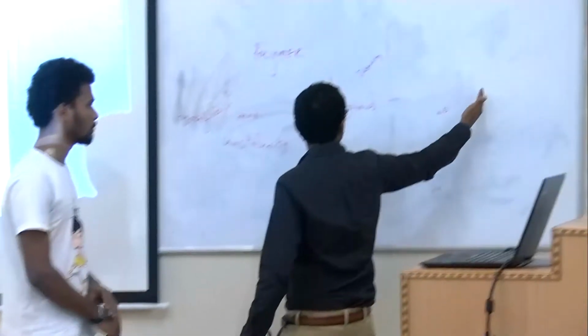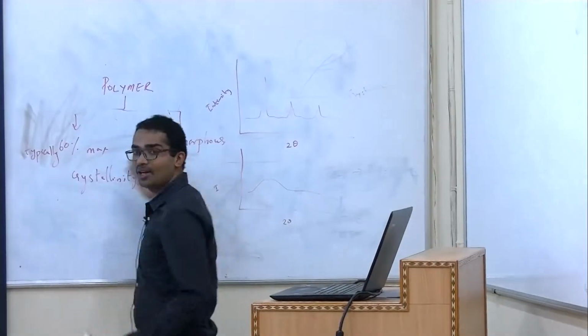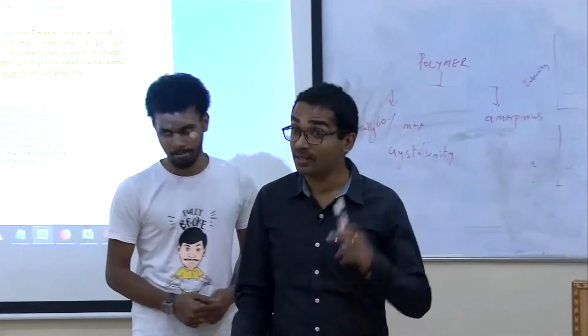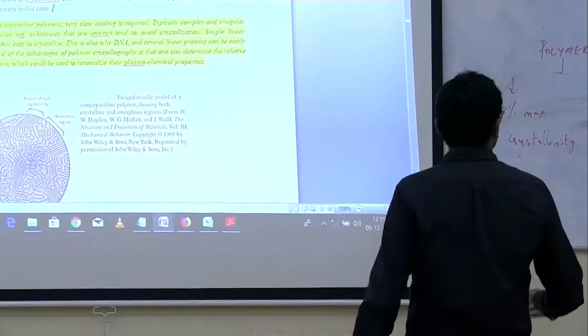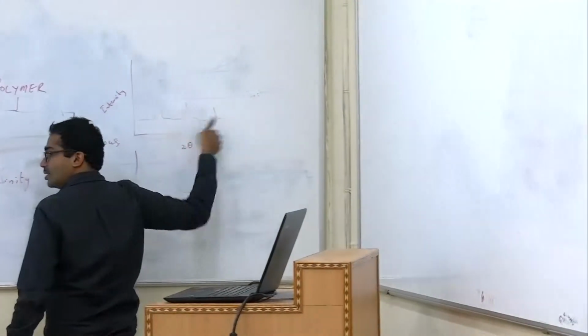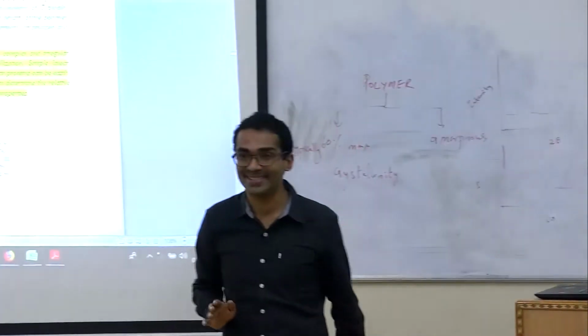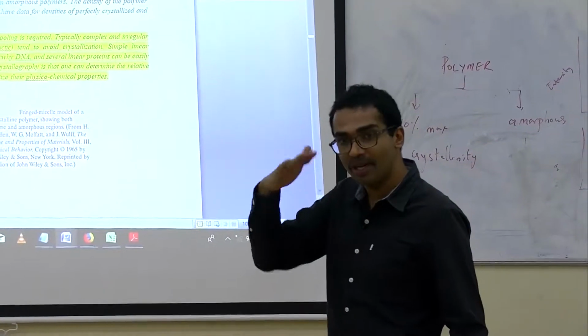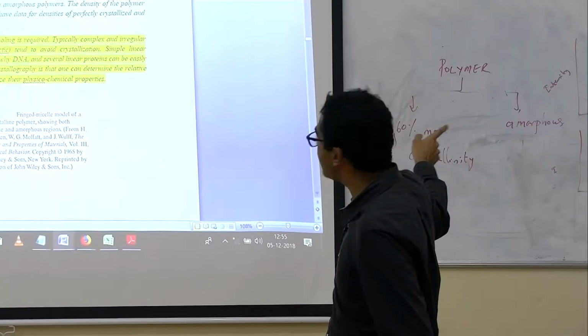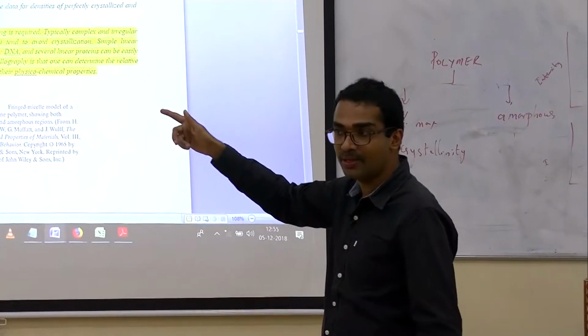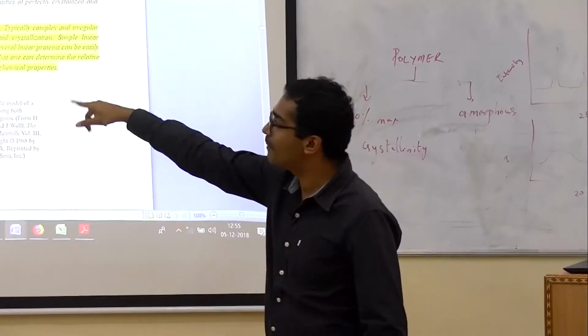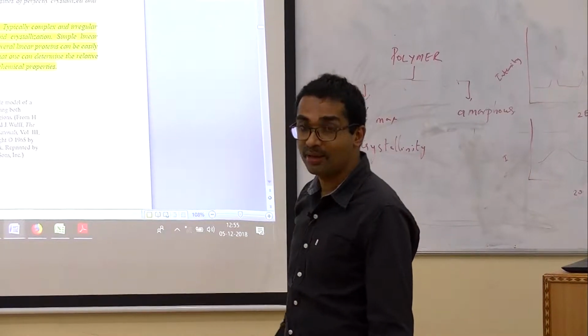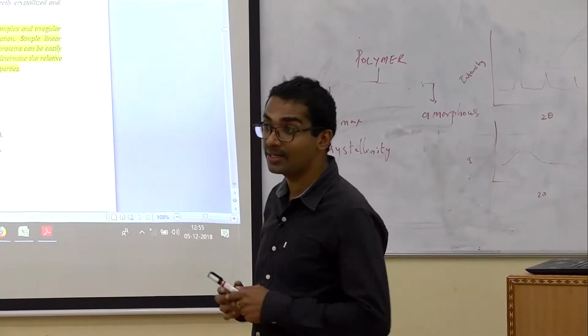Here D is very, very large, so the theta can be very small. That is why you do small angle X-ray scattering. So this 2 theta can be as little as 10 degrees, for instance, and you can get all these peaks. But in the case of crystalline solids, this 2 theta will go all the way to several tens of degrees, and that is a big difference. That has to do with the fact that the periodicity is larger in this particular case. Small d, the interplanar distance, is much larger between 2 polymeric chains when compared to between 2 atoms in an inorganic crystalline solid.